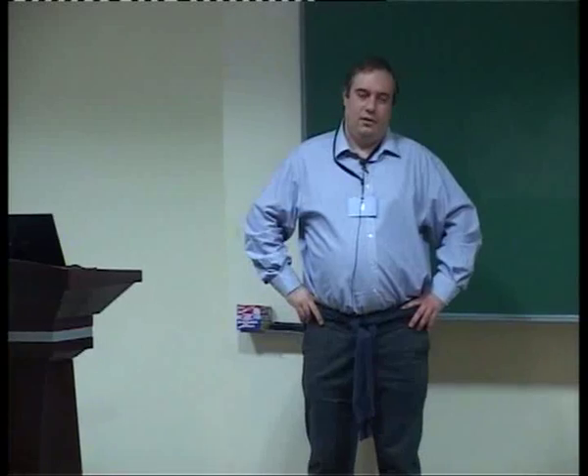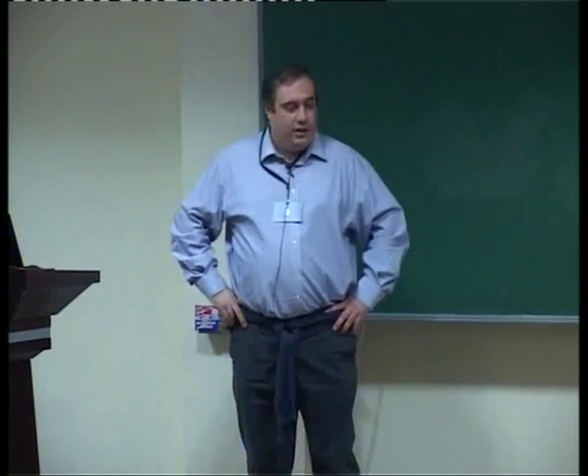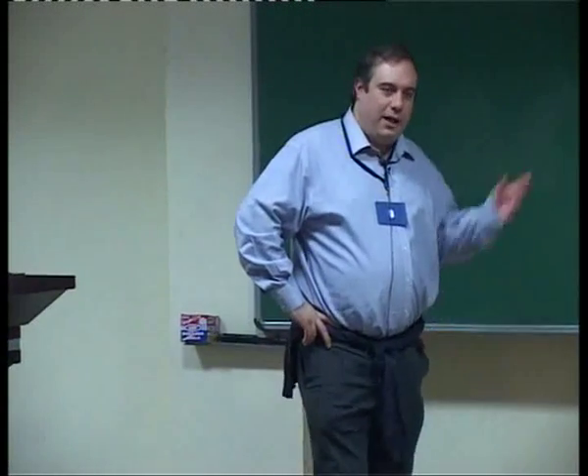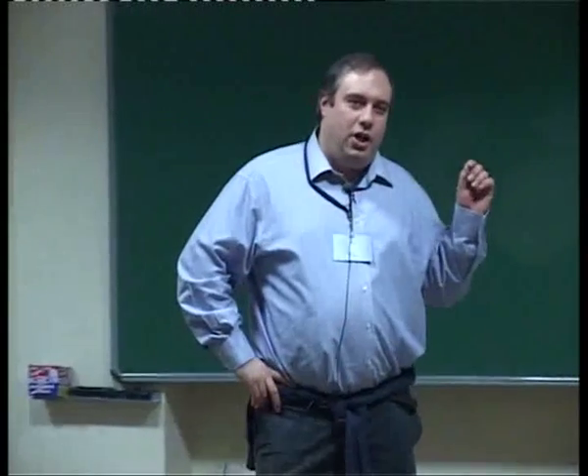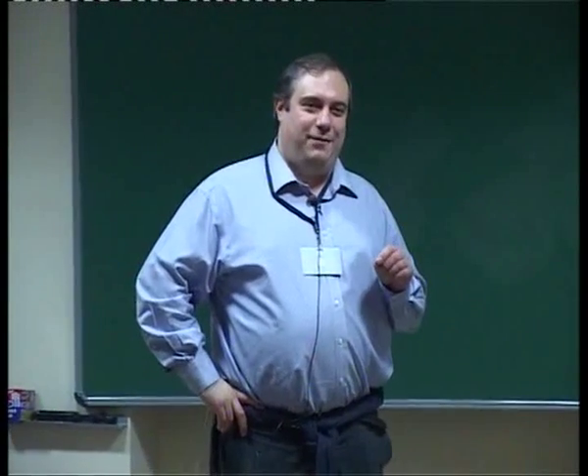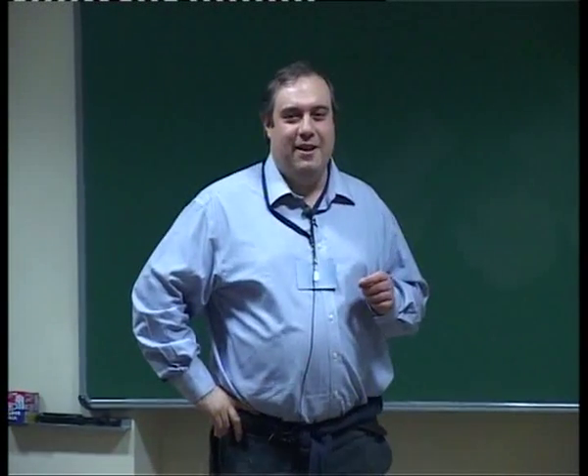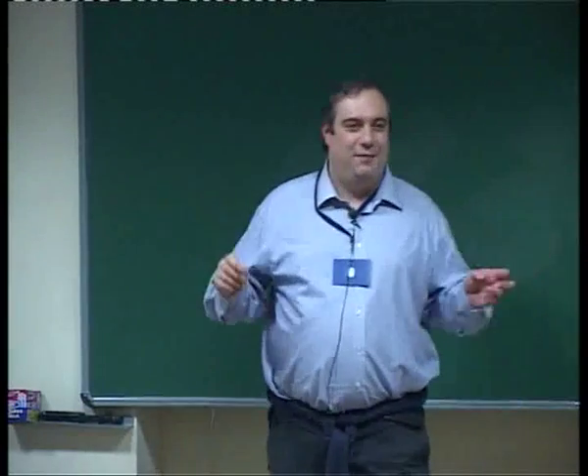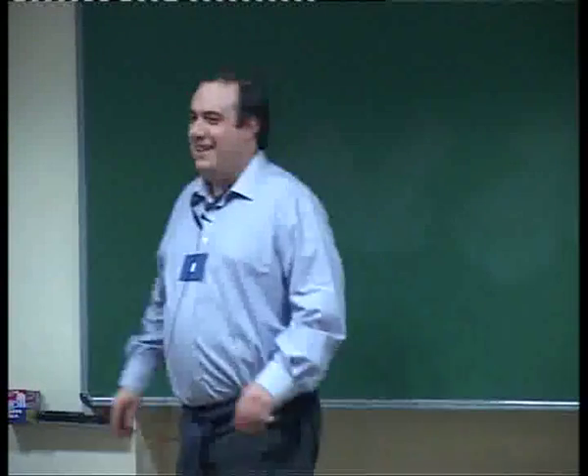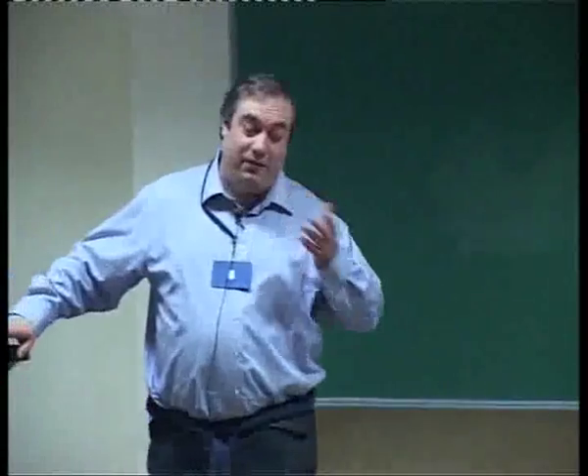Does it matter if you use single layer, bilayer graphene? Yes, it does change, and of course, with bilayer graphene, to be honest, the image was done with the bilayer graphene because we get much better results. It's graphene either way, but if you increase the number of layers, it's better. If you have too many layers, then they don't work anymore because they absorb all the light. So 2 layers seems to be better than 1.